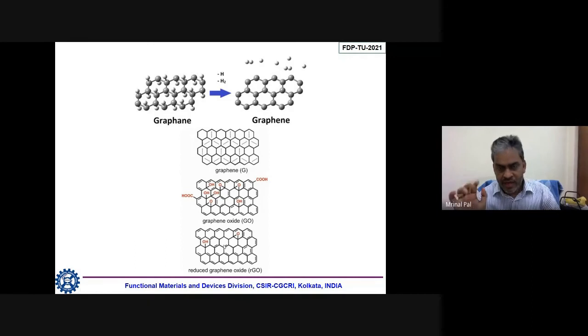So I hope that you can understand the difference between graphene oxide and reduced graphene oxide. And strictly speaking, there is a difference in properties between graphene and reduced graphene oxide. Both of them are graphene, but if you look at the structure, in the case of reduced graphene oxide, there is a possibility of having some defects and also some oxygen and OH groups. So that will bring some different properties as far as the pure graphene structure is concerned. That's why graphene is different, reduced graphene oxide is different, graphene oxide is different.